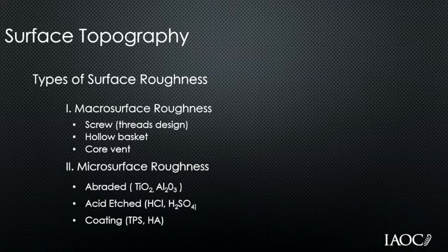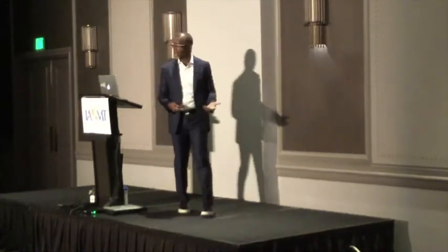Now, another thing that has been done with implants, whether they're ceramic or titanium, is the surface of the implant. And there's two types of things that you have to take into consideration: the macroscopic and the microscopic. Macroscopic is like the thread design, the thread aggressiveness. One of the latest implants on the market today, the SDS, has very aggressive threads. And you can place it immediately after an extraction, and you get good primary stability. 12 years ago, 11 years ago when I started, there was none of that. There were just threads with a smooth surface, and they were not aggressive enough, and the primary stability wasn't very good. But now you have some systems that have very aggressive threads that allow you to do things like immediate placement and even immediate loading. Okay? With the earlier ceramic implants and immediate loading, there was a 70% chance of failure of the implant. So you have to protect that implant.